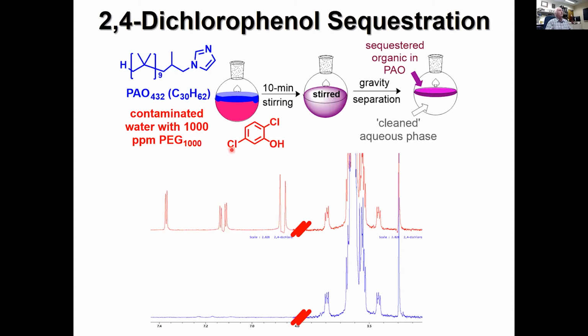...like this 2,4-dichlorophenol, if you put it in water, it's going to contaminate the water at a low concentration. If you take something like a C30 hydrocarbon—really just a low viscosity form of motor oil—we can make another polymer that's got an imidazole on it. Imidazole is a good base and can coordinate or hydrogen bond to this phenol. This material in the hydrocarbon phase—the hydrocarbon, of course, isn't soluble in water. It's a C30 hydrocarbon, so it's only soluble at less than a part per billion level.